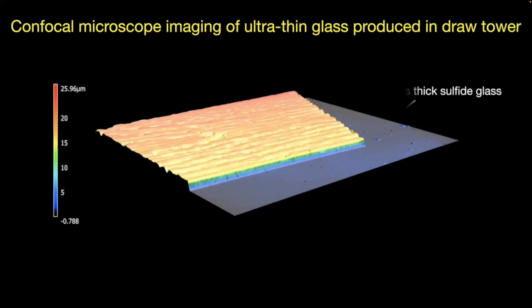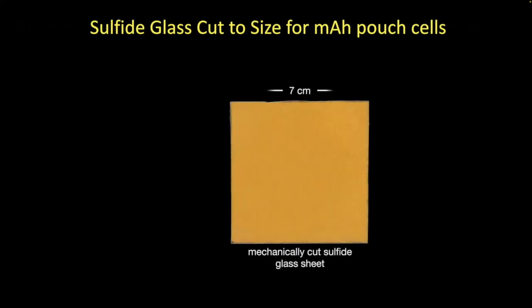And when we pull the glass, of course, this is quite thin. So we image it with a confocal microscope. This is a laser microscope. And you can see here that we can pull glass down as thin as 15 microns. So we're getting down to the dimensions that we need for very high energy density cells. For the time being, we are mechanically cutting the glass, so it's a bit of a rough edge. We are about to transition to laser cutting of these glasses.